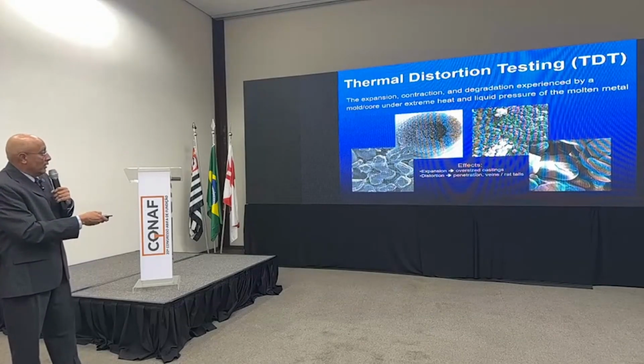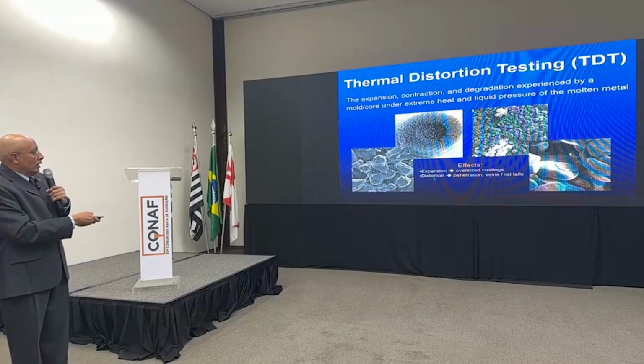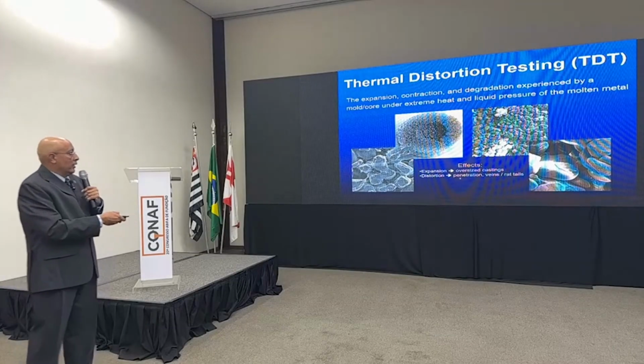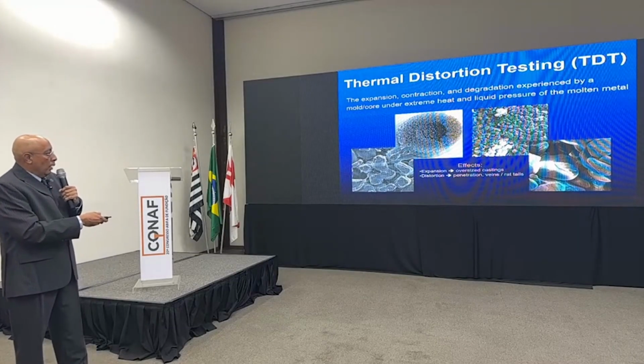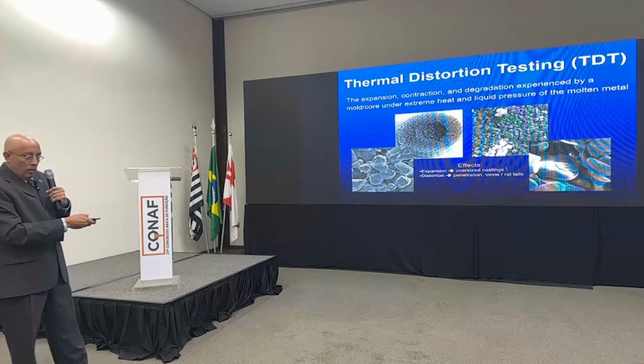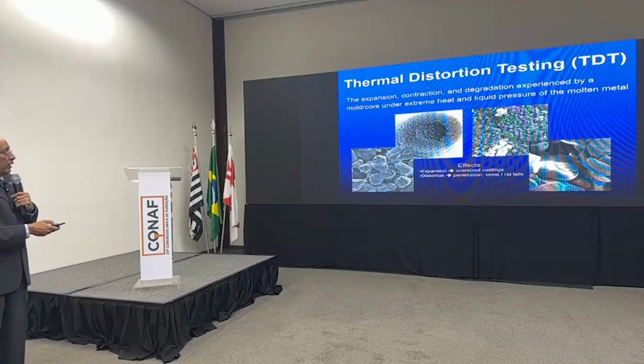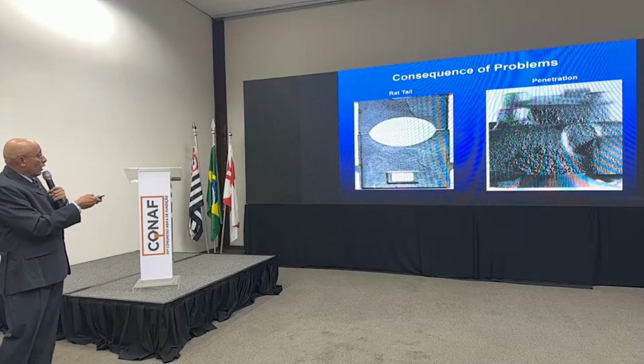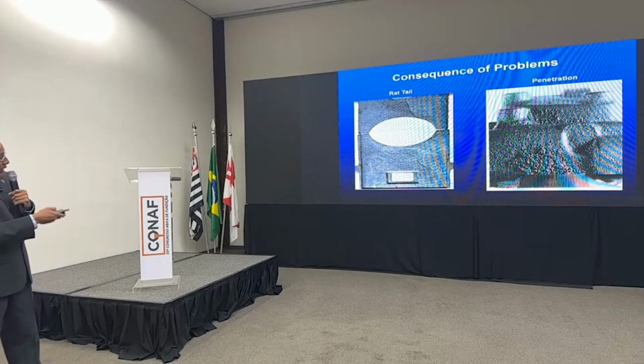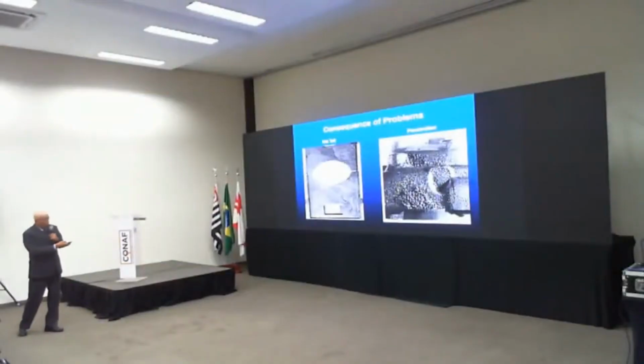could cause oversizing of the casting, but the distortion issues related to that crack can be penetration, vein, rat tail defect in the casting. So this is what a rat tail would look like, a fin. That's what we may need to grind off in the finishing room or do some grinding or machining on these surfaces to improve the surface quality.